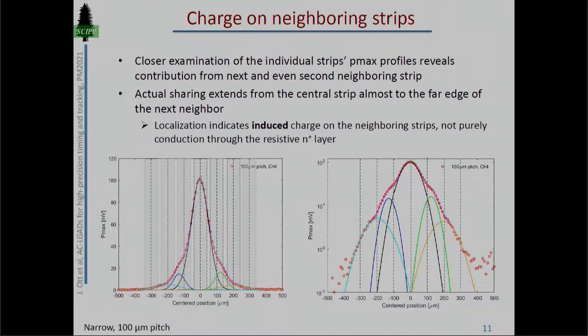Naturally the charge sharing is due to the common N+ layer that connects all the pads, but it's not quite as straightforward as just having a hit in one segment that then shares the charge with the neighbors. There is charge directly induced also on the neighboring strips and then fed back. This also scales with the pitch, for example.